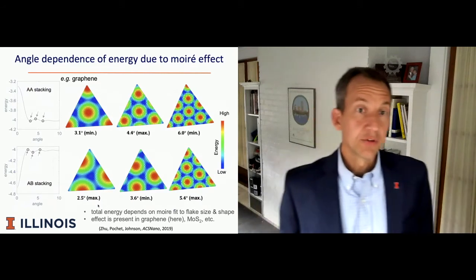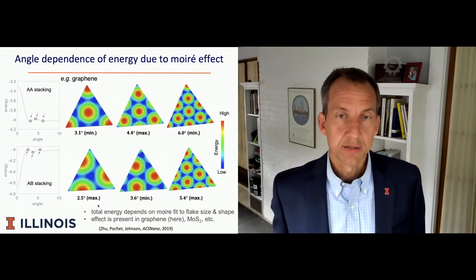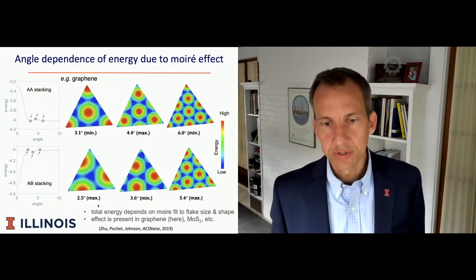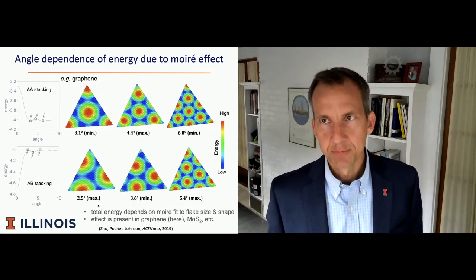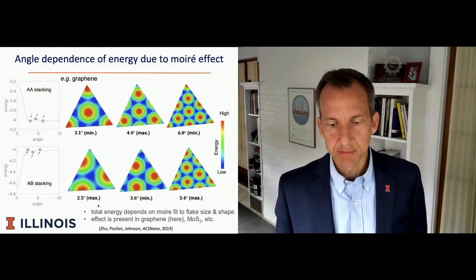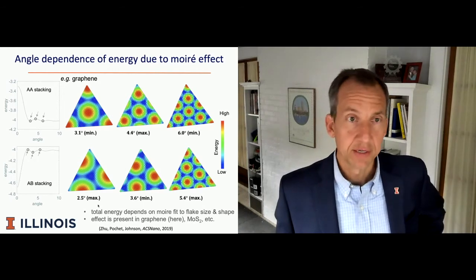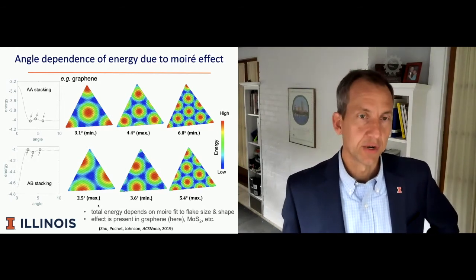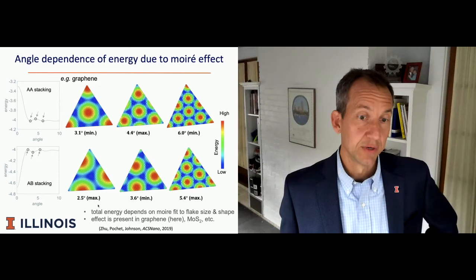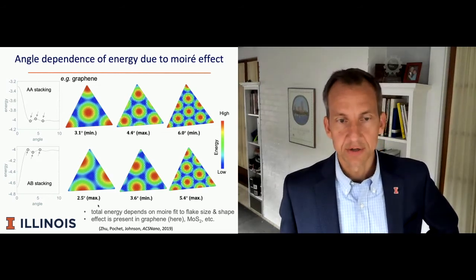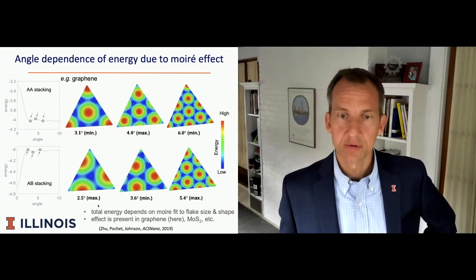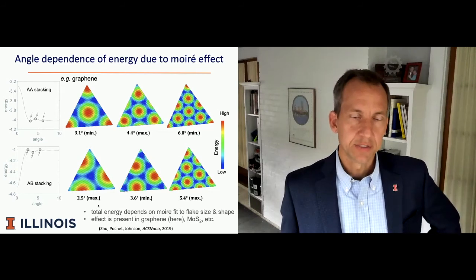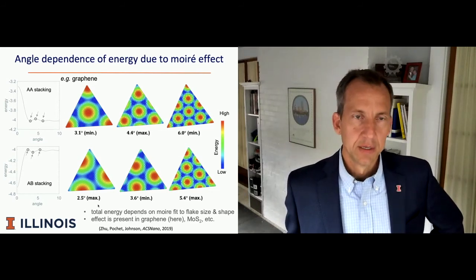So indeed, the angle dependence of the energy is due to a moire effect. And so that's what this slide shows. Here, we're looking at graphene. And as I said, we see many of the same things for graphene bilayers as we do for MoS2 bilayers, and indeed for any 2D material stacked on any crystalline substrate, including a bulk crystal. And I actually spoke about that in the talk yesterday.